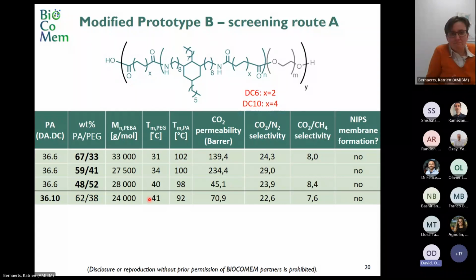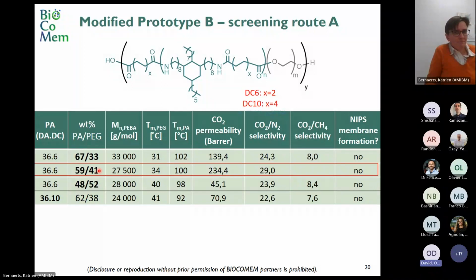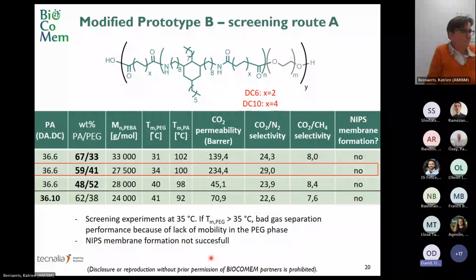Yeah, so we can see carbon dioxide permeability, which is higher for higher polyether glycol content, at least like the second line. Then the third line is lower, but then the polyamide is different, I think. And the PEG has a melting point above the testing temperature. Yes, so it's more crystalline. This is why the permeability is lower. So ideally for these membranes, we should have the melting point for PEG lower than the testing or the application temperature. For carbon dioxide separation and post-combustion processes, it's around 30 to 50 degrees. It can vary during the year. So yeah, we should have the polyether melting temperature lower than 30 degrees.